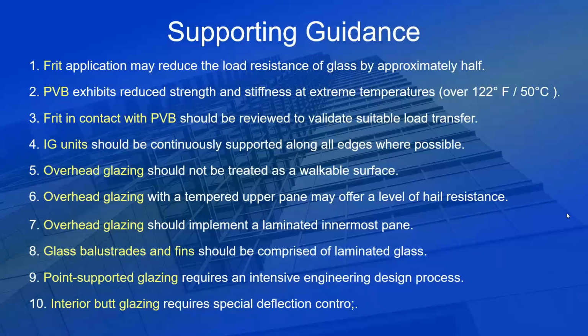Ceramic frit application can reduce the load resistance of glass by approximately half. PVB interlayers exhibit reduced strength and stiffness at extreme temperatures, over about 50 degrees Celsius. Frit in contact with PVB should be reviewed to validate suitable load transfer from the glass surface to the PVB, to the inboard light. IG units should be continuously supported along all edges when possible. Overhead glazing should not be treated as a walkable surface regardless of what the building developer requests. Overhead glazing with a tempered upper pane may offer a level of hail resistance, and overhead glazing skylights should implement a laminated, heat-strengthened innermost pane.